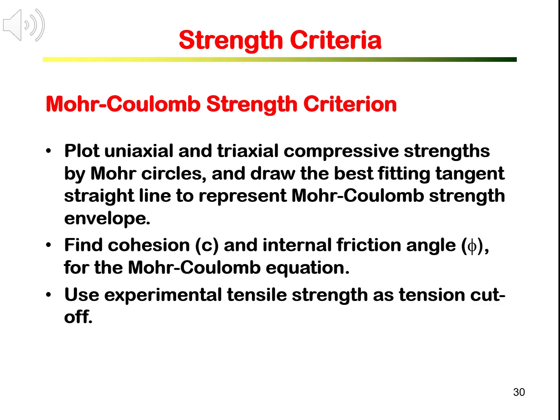For the Mohr-Coulomb strength criterion, what we need to determine is the cohesion C and the internal friction angle phi. First, we plot the triaxial and uniaxial compressive strengths by the Mohr circles and draw the best fitting tangent straight line to represent the Mohr-Coulomb strength envelope. From the strength envelope, we can find the cohesion C and the internal friction angle phi for the Mohr-Coulomb strength equation. We learned in session 2.5 that the Mohr-Coulomb equation gives much higher tensile strength. Therefore, we use the actual tensile strength obtained from the test as the cutoff for the strength envelope on tension.